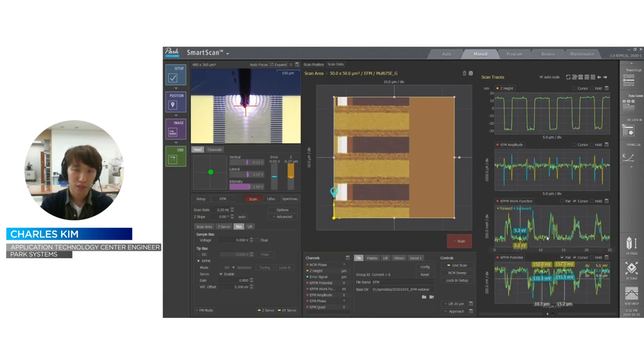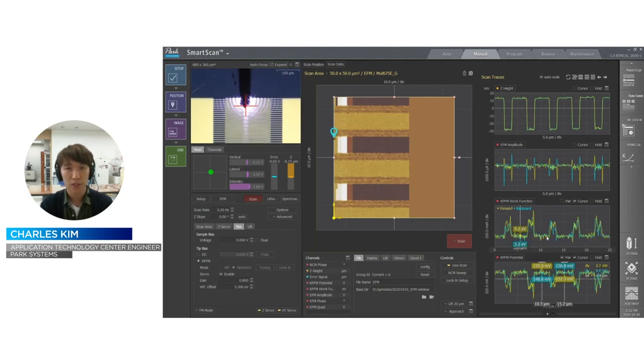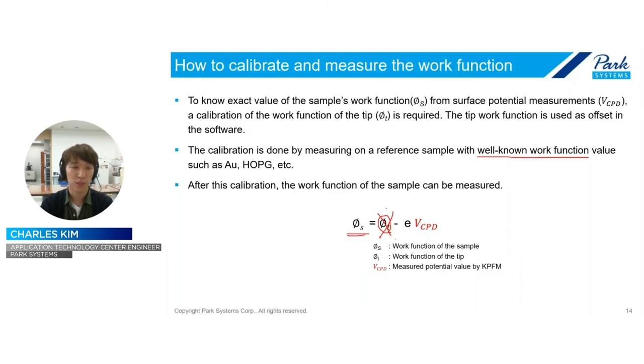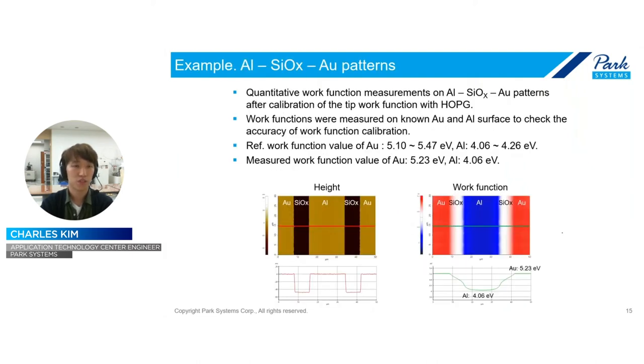After calibrating like this, if you measure your unknown sample, then that value is the real work function of your sample, because the work function of the tip is compensated by that offset value in the smart scan. So this is one example of the work function calibration. The sample has gold and aluminum and gold, and in between them there is silicon oxide. When I calibrate by using the gold, then the aluminum surface is as follows. That value is very similar to our expectation. So this is the way to measure the work function by using KPFM.